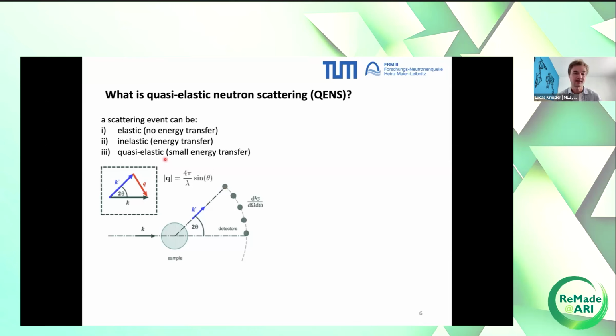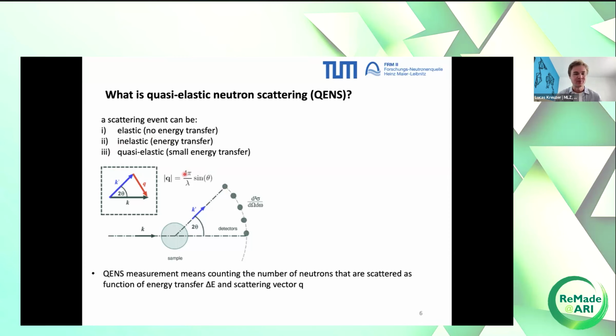And if it's in this quasi-elastic range, then we would be interested in this. So basically, QENS is counting the number of scattered neutrons as a function of energy transfer. This is measured by the time of flight, and the scattering vector Q. This is measured by these neutron wave vectors.